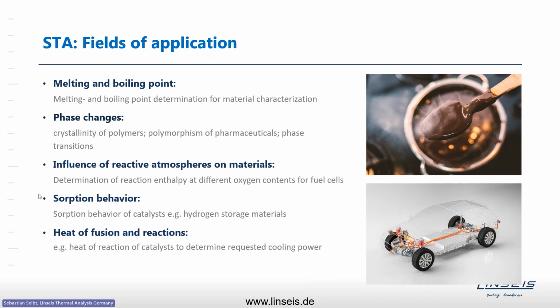Something that's very interesting for a TG-DSC as well is the sorption. Of course, a TGA shows sorption regarding the mass change. So you can do gravimetric sorption. You put a sample in, you apply a certain gas, the mass changes by gas uptake. So that's where sorption is usually recorded. You can do it volumetric, but with our instruments, mainly you do it gravimetric, like storage capacities of hydrogen storage materials and stuff like that. And in case of TG-DSC, you can also get information about the heat of sorption. So how much energy is released or consumed during absorption and desorption.